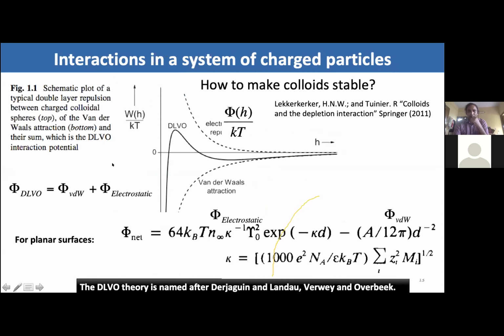Now, one also has to be aware of the interactions in a system of charged colloids, and the total potential, also called the DLVO potential, which is the summation of the van der Waals forces, which are always present whenever you're dealing with a molecular system, plus an electrostatic repulsive term, which comes because of the charges on the particle surface. The van der Waals force and electrostatic force can take different forms; the expressions differ depending upon the particle geometry, whether we are dealing with spherical particles in the fluid or disc-like particles, and so on.